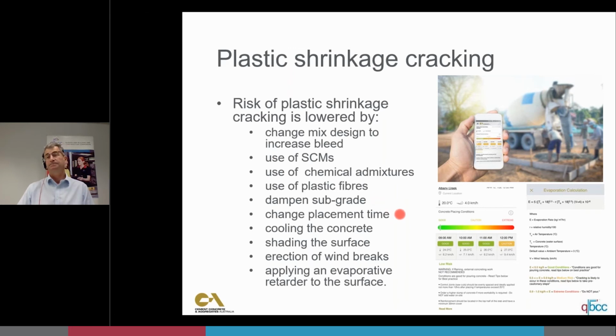Change the placement time. It's not uncommon in the summer for us to be delivering concrete at 3 or 4 in the morning, so we avoid the risks of plastic shrinkage cracking. Cooling the concrete. Sometimes we'll cool it with chilled water or ice. That'll give you longer placement times, better slump retention, and less risk of plastic shrinkage cracking. Shading the surface, erection of windbreaks, and as I said, the use of an evaporative retarder.